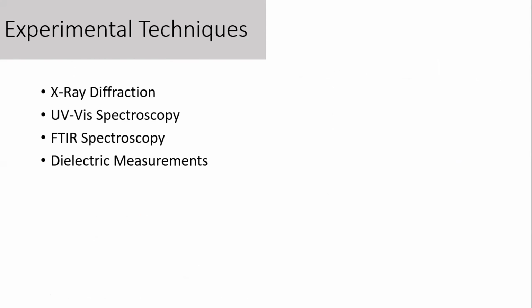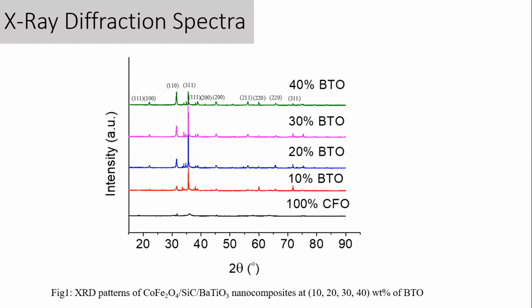Let's look at the results of the first experimental technique, that is X-ray diffraction. On the screen is the X-ray spectra of our nanocomposites. I would like to highlight this: this is the 100% cobalt ferrite, and here we have introduced 10% barium titanate, 20% barium titanate, 30% barium titanate, and 40% barium titanate. The other two components were kept in equal percentage. For example, if here we have 10% barium titanate, then 45% silicon carbide and 45% cobalt ferrite. In the same manner, we created this nanocomposite series.